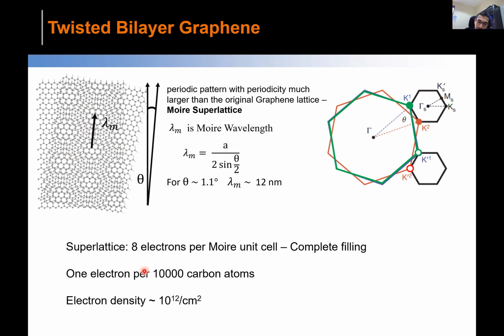And in fact, that density corresponds to the order of 10 to the power 12, which is achievable in the experiment. That is very important to me as an experimentalist, and very appealing. Even though with single layer graphene there are interesting things you can do, you cannot achieve that. But with twisted bilayer, by making this angle and this new Moiré band structure, you can easily dope the system such that you can study the full band.